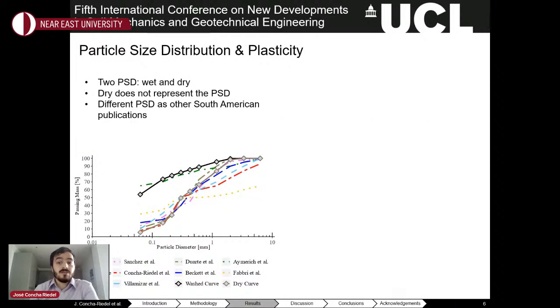For the particle size distribution, two methods were used, wet and dry sieving. The washed curve showed a 50% content of fines and a well-graded sand, whereas the dry sieve resulted in a poorly graded sand. The dry sieve method did not represent the intrinsic properties of the soil, as we will see later on. However, this result is useful for understanding the soil's particle size distribution when it's dry, as clusters of particles may bind together to create larger arrangements.